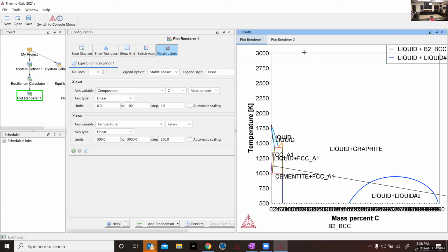You can also sometimes see, and maybe even in this system, that at really high temperatures, way up here, say above 3,000, at 3,500 to 4,000 degrees, an inverse miscibility gap, where we've got a single-phase liquid, and then this big old semicircle up here where the single-phase liquid is supposed to separate into two different liquids. You can keep your inverse miscibility gap. I don't want that. That liquid plus liquid number 2 would never happen. That is an error associated with the way that the thermodynamics have been defined and optimized. And you can have similar things that happen way up here. A good thermodynamic assessor will take into account as much of that as they possibly can.